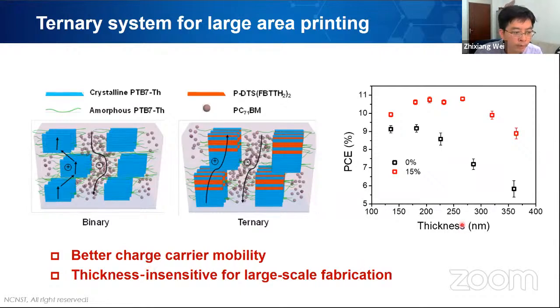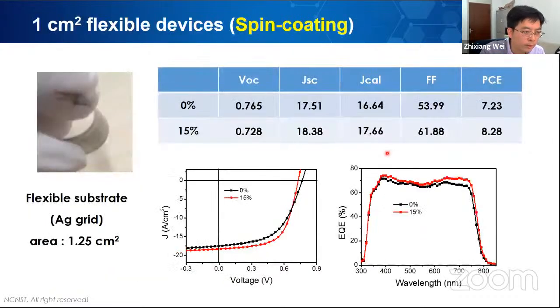Therefore, it's quite good for large area fabrication, because in large area printing, you cannot print at the 100 nanometer scale really precisely. So we can show you, if we make a 1 square centimeter flexible device by spin coating, we can get 7% in the binary, but 8% for the ternary. You can see every curve is quite good.